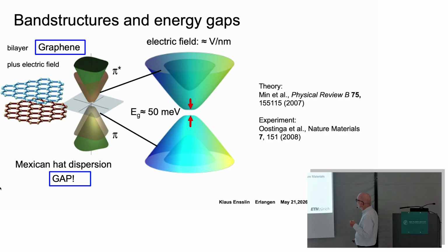Okay, now if you blow this up a little bit, you see that the originally parabolic dispersion is no longer fully parabolic. You have a band gap which is of the order of magnitude of 50 milli-electron volts. That's a small number if you compare to silicon and germanium and gallium arsenide. But if you work with millikelvin temperatures in a dilution refrigerator, then this is a huge energy scale. And for all practical purposes, it's a reasonable band gap.